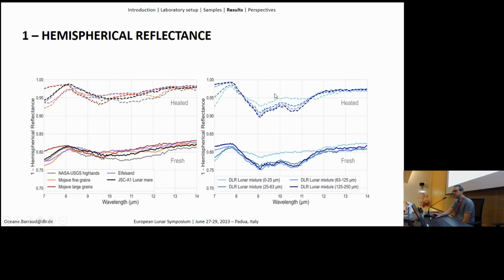And here on the right panel, you will see the comparison of the different grain sizes. So you see grain size has an effect. It's not huge, but especially when you jump from the very fine to the intermediate and larger grain size, you see that there is really, especially in the Reststrahlen bands region, a huge difference.